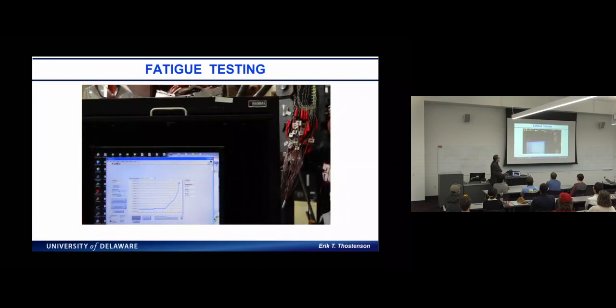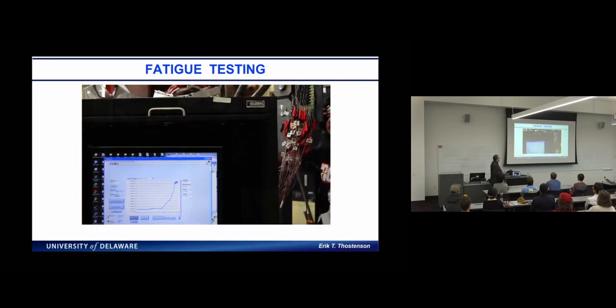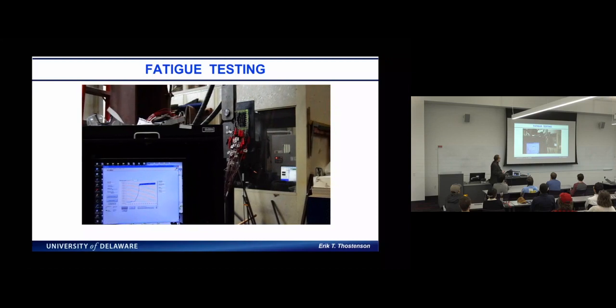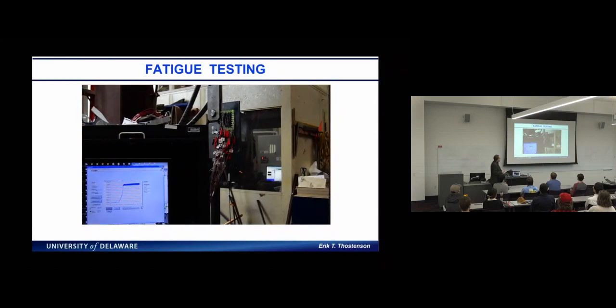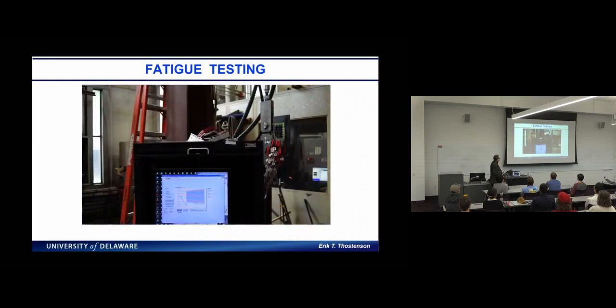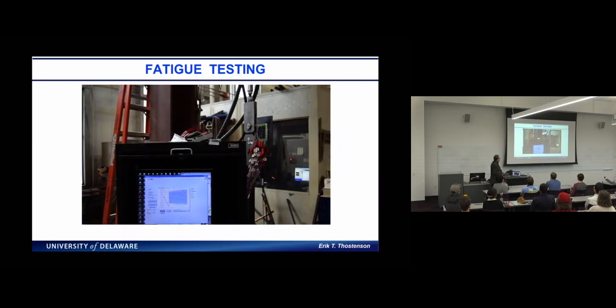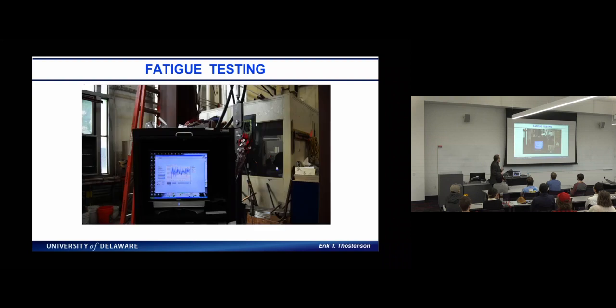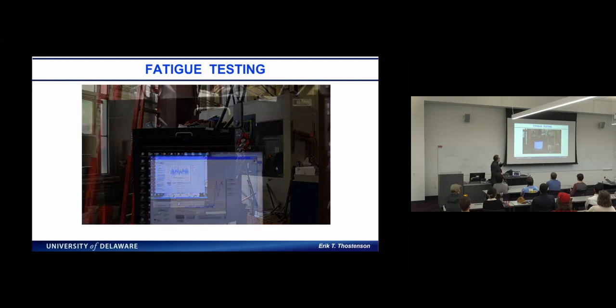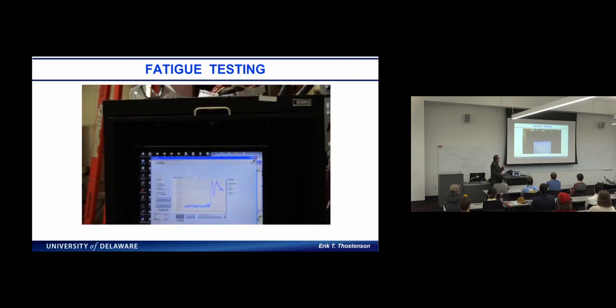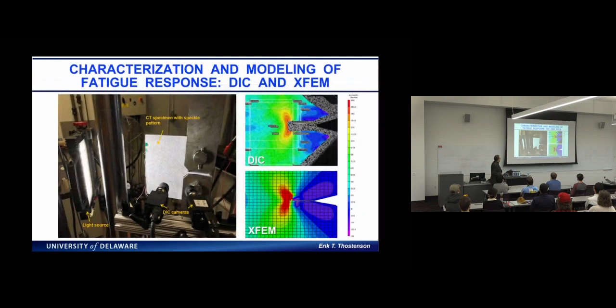So we're just starting the initial test. But you can see the sensor is integrated into the patch. And you can see that we're measuring, and we can measure that. And we're fatiguing it, but we can sense that fatigue damage or fatigue in real time. And then over time, as that crack grows, we see the sensor fragment, and we can actually monitor that.